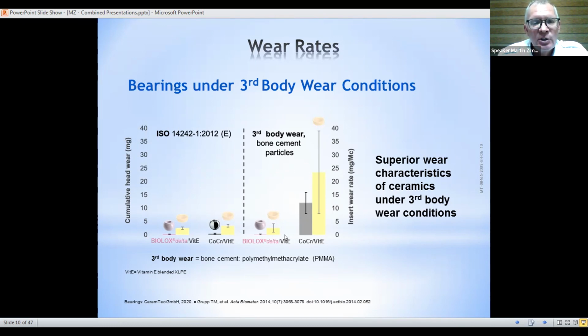But if you go, as shown here on the right-hand side, into what we call suboptimal situations, typically when you have bone cement particles or other particles coming in between the articulation, then you see a drastic difference in the wear conditions if you have cobalt chrome and polyethylene components. Not only is the polyethylene wearing more, but also the cobalt chrome, and there is the whole problem of the release of cobalt ions, cobalt particles in the body.